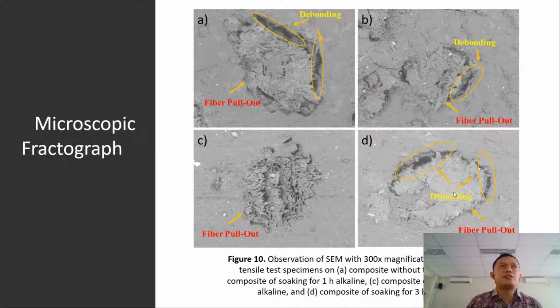And talking about the microscopic fractographs, we see there is a debonding fracture, and also fiber pull out. This is SEM with 300 times magnification, where we can see there are many defects in fiber pull out and debonding. Further research needs to be done in the form of fluctuation in fiber orientation, matrix selection, merging biaxial and triaxial directions, and advanced methods such as vacuum bagging process, vacuum infusion process, and compression molding.